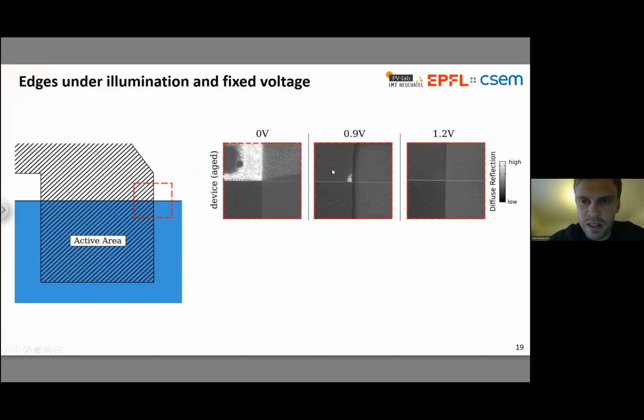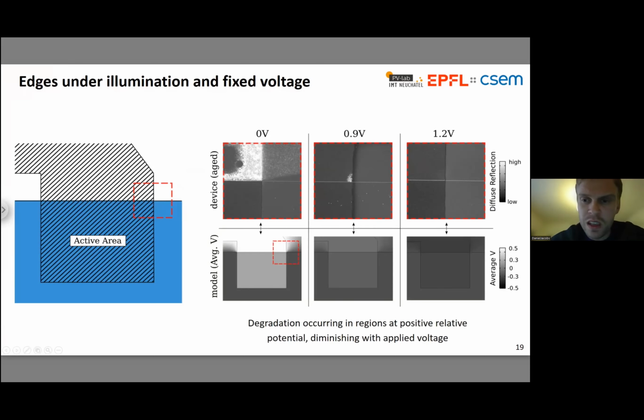And this degradation is indeed decreasing with applied voltage. So as we go to 0.9, you can see that there's a small little spot of damage happening at that corner, and at 1.2, it disappears. So it looks as if nothing much is happening there. And when we look at our models, it's this region where the ITO boundary finishes that's actually at the highest internal potential, so at the most positive internal potential at 0 volts, which means that the degradation is occurring preferentially in regions at positive relative potential, okay, and diminishing with applied voltage.